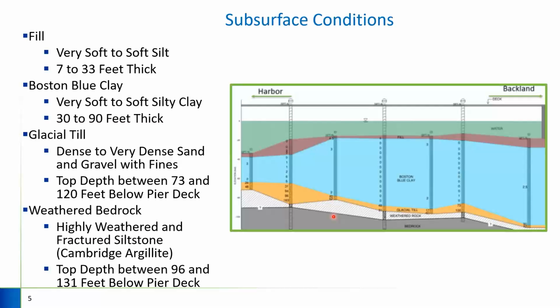The Boston blue clay, as you can see in the figure on the right, had mostly weight of hammer material, which you would expect, and ranged from about 30 feet at the inside of the harbor to about 90 feet deep at the sheet pile wall. Then finally, you get into your bearing strata, which are typical of this region, where you see glacial till with very dense sands, gravels, and fines with mixes of cobbles and boulders in some locations. And that layer was about 70 to 120 feet below the pier deck.